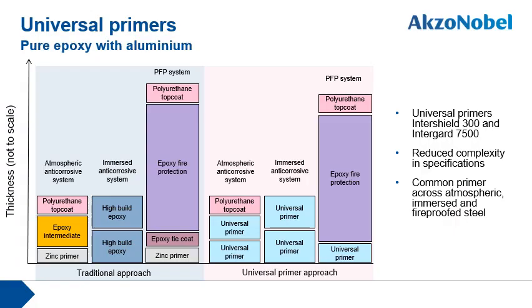We start with a deeper look into universal primers such as Intershield 300 and Intergard 7500. Now, these products can be used in multiple end uses such as atmospheric exposure, immersion, and as a primer under passive fire protection. The key attribute is that they provide as good, if not better, anti-corrosive protection than the traditional products that they replaced, such as zinc-rich primers for atmospheric end use.